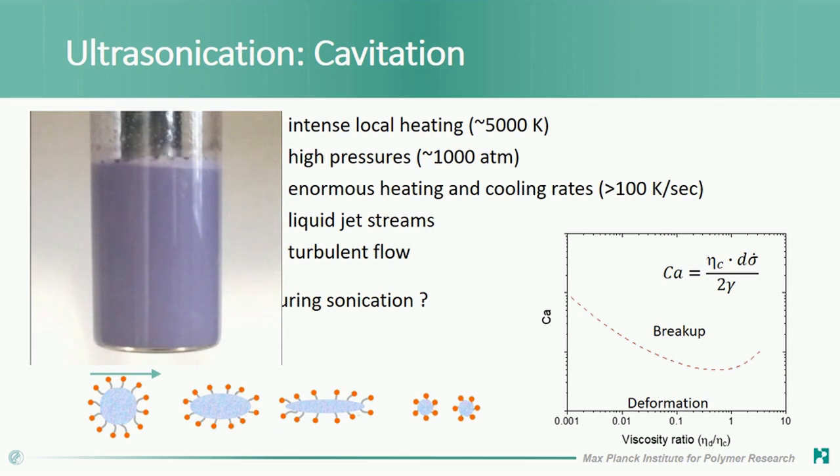And then the energy that you have in the sum of the cavitation events that you observe will be much different. And then scaling the sonication time with different sonotrodes is not trivial, and you just really need to try a range of different conditions if you want to change the sonotrode.